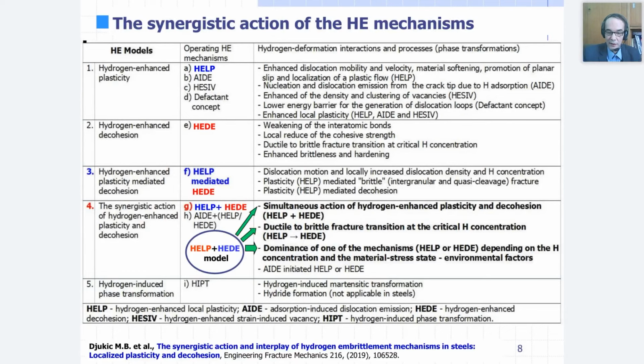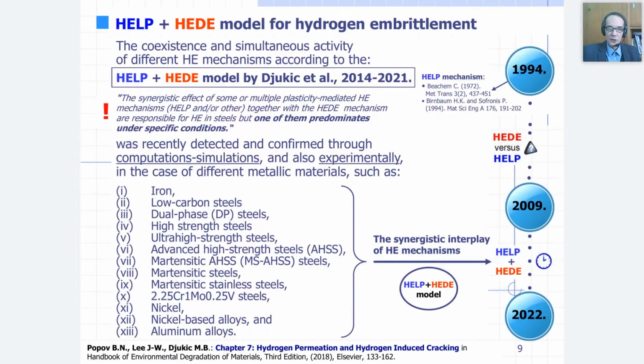and also important is the material stress rate and also some environmental factors. So, as a summary, our HELP plus HEDE model was recently confirmed in various metallic materials by experimental tests and also through computations and simulations. So it is confirmed in various types of steel, as you can see, high strength steel, advanced high strength steel, dual phase steel, low carbon steel. Also it is confirmed in iron, and more recently in nickel-based alloy and aluminum alloys.